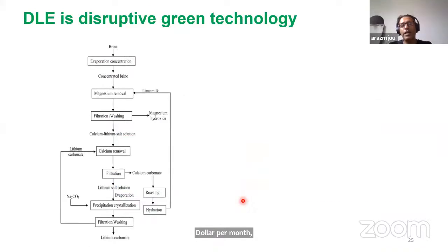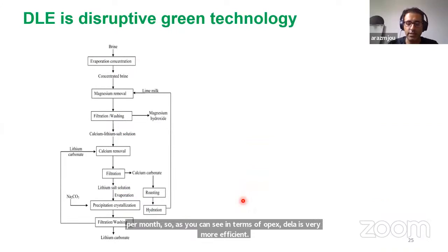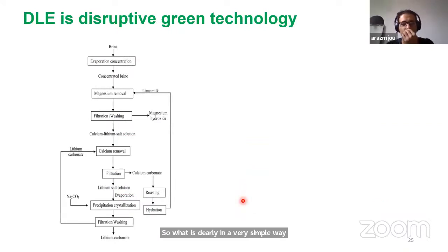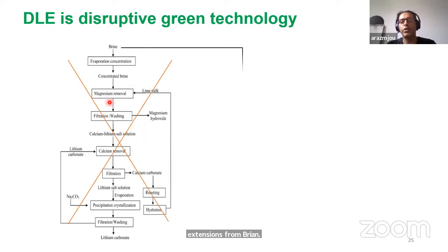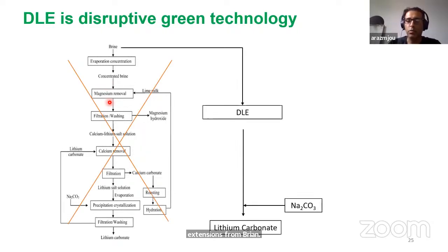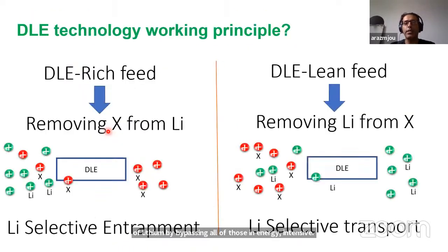So what is DLE, in simple words? This is a typical flow sheet for conventional extraction of lithium from brine. Basically, with DLE, you can remove all of those stages, and you can add sodium carbonate to produce lithium carbonate. So this is basically what DLE does in extraction of lithium, by bypassing all of those energy-intensive unit operations.